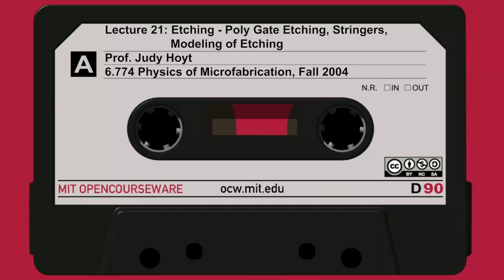And there were apparently small oxide inclusions at the surface of the wafer when the etch was started that didn't get fully removed. Those small oxide areas act like little micro masks. They were not intentionally put there, but there's just a little bit of oxide here and there. So a breakthrough etch wasn't used. As a result, if the etch that you're using is highly selective to oxide, it'll never etch it. Instead, you end up with little posts, which look like little blades of grass.